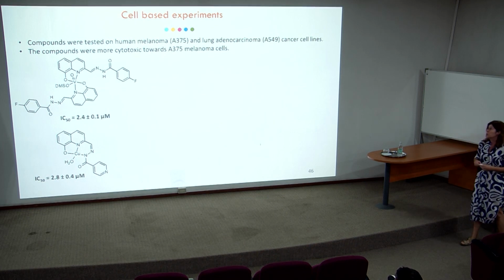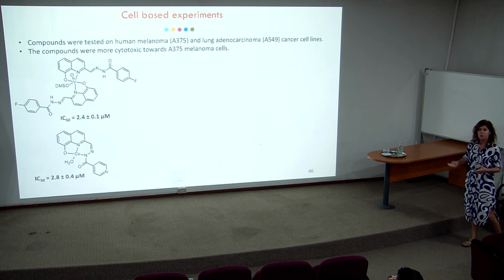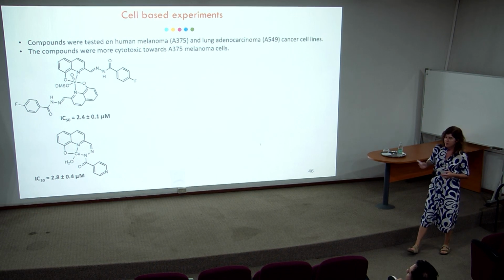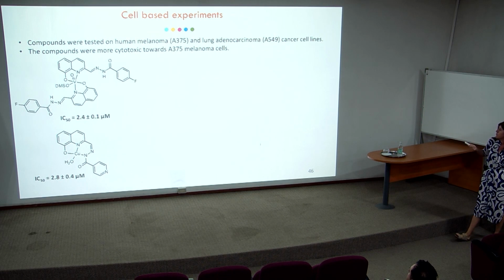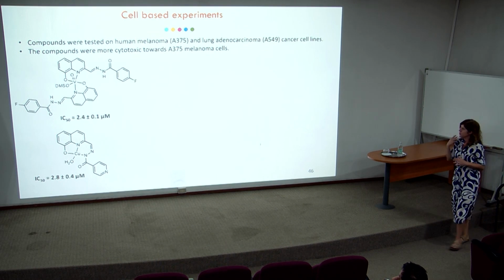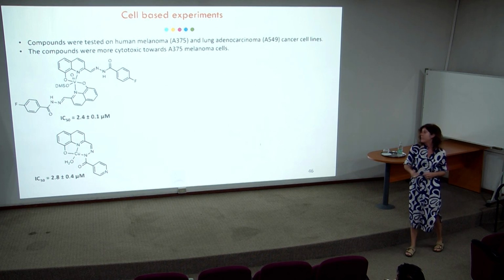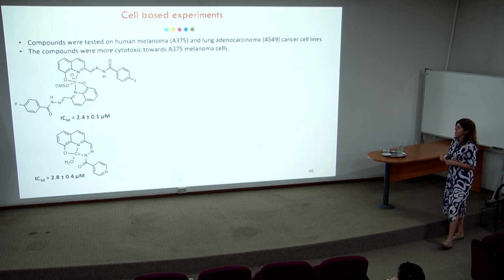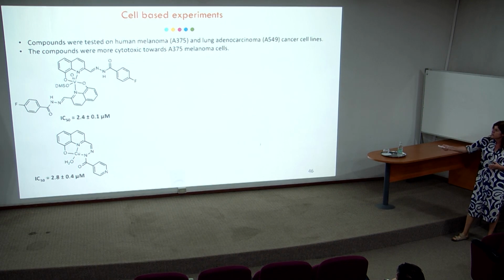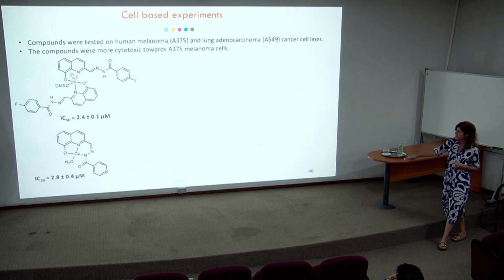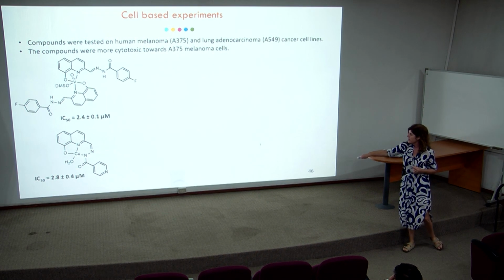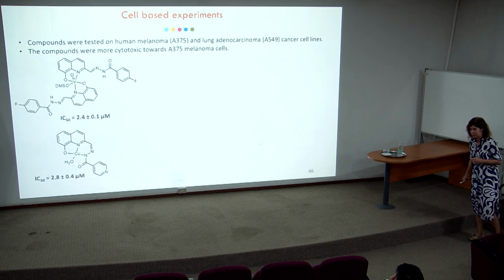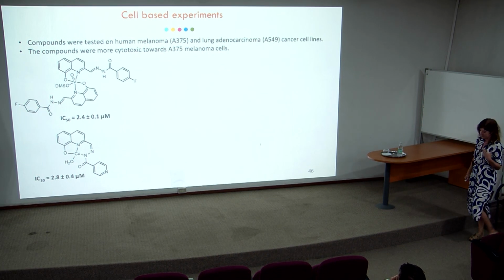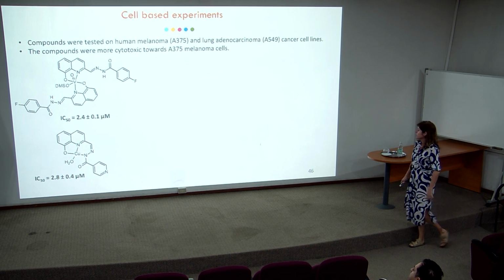And then I'm not going to show you details. These are many compounds. We evaluated their cytotoxicity in human melanoma cell lines and lung adenocarcinoma, but they were much more cytotoxic towards the melanoma cells. The compounds which showed the best results in the case of vanadium was the fluoride substituted complex, 1:2 metal ratio, and in the case of copper was this one that has a pyridine here. So this is derived from isoniazid, which is a compound that has been applied in different fields as therapeutic.